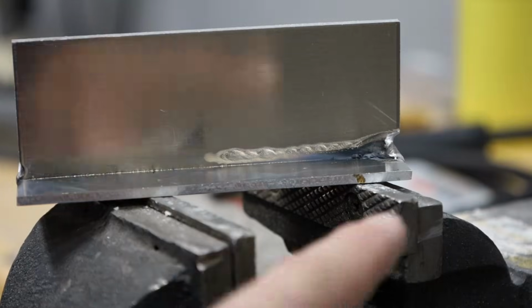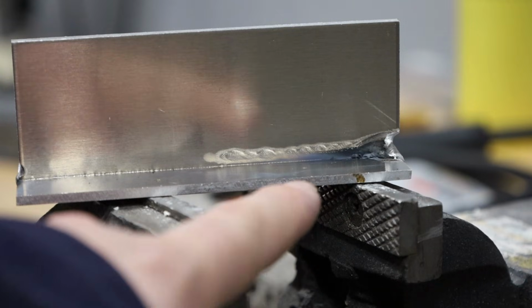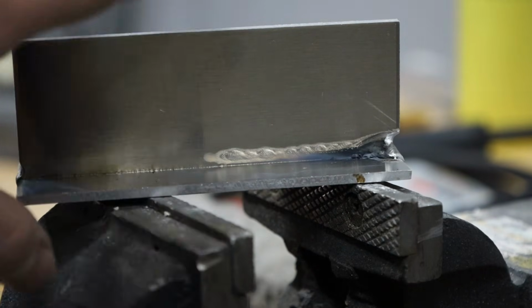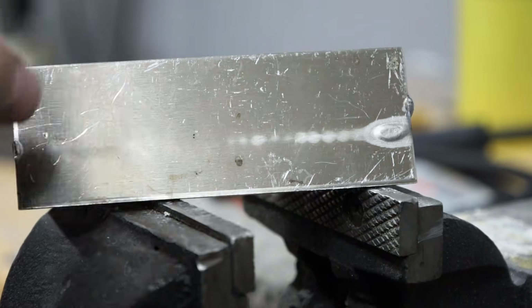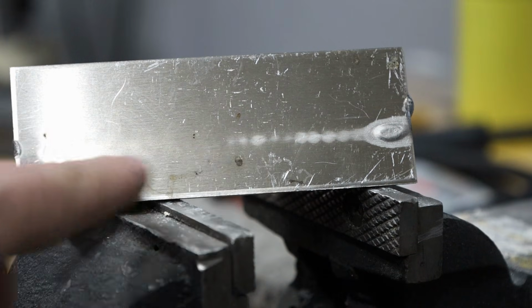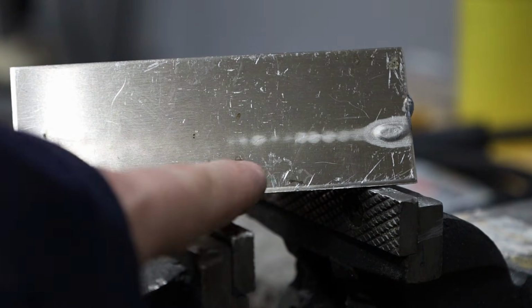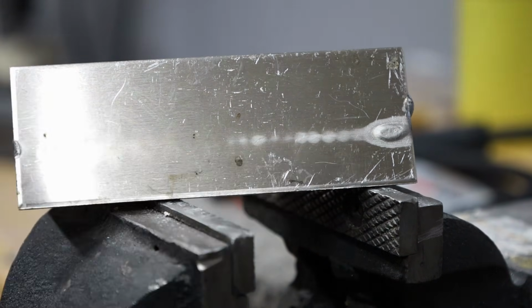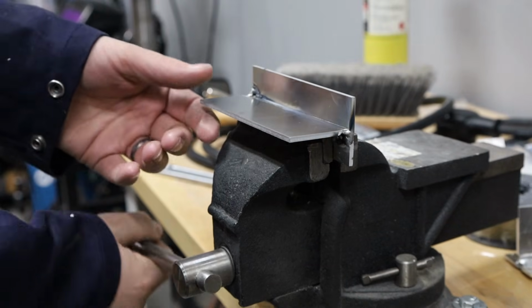So let's take a look at how this is structurally. See here on the back, you can see where I was getting good heat and penetration in through there. It's starting to melt through on the back and the bottom. You're seeing those heat indications there, where on the first half of the weld, you don't see any of that. So it makes me question how structurally sound it is.